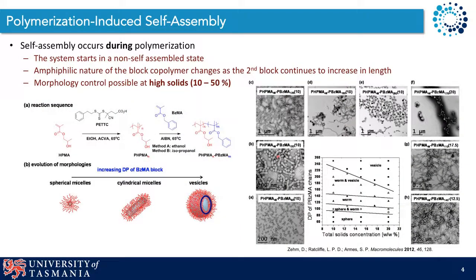Polymerization-induced self-assembly, or PISA, however, has been the real revolution in this space to prepare composites or polymer nanoparticles of a variety of morphologies at high solids content. The key point is that the system starts in a non-self-assembled state, using advances in techniques, primarily through RAFT or ATRP polymerization methods. We first grow a solvophilic block, which is soluble in the reaction medium, and then we undergo a chain extension process with a solvophobic monomer, leading to the onset of self-assembly. As we increase the length of the core forming block, we ultimately achieve higher order structures such as cylinders, worms, and ultimately vesicles.